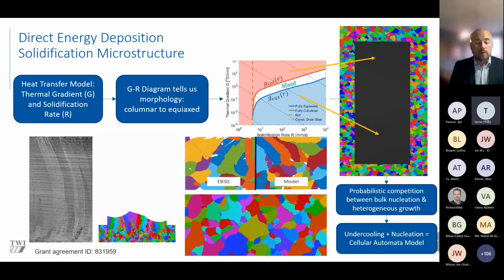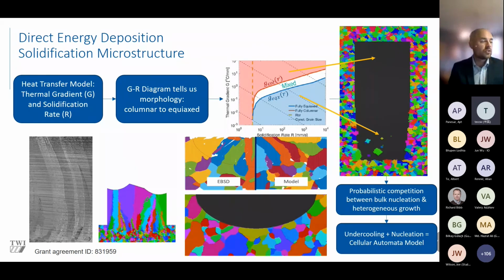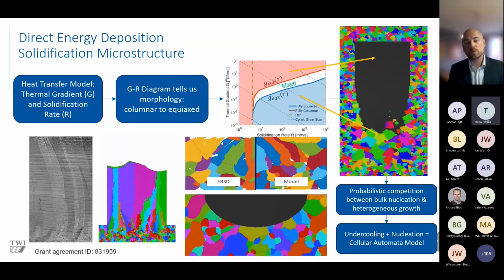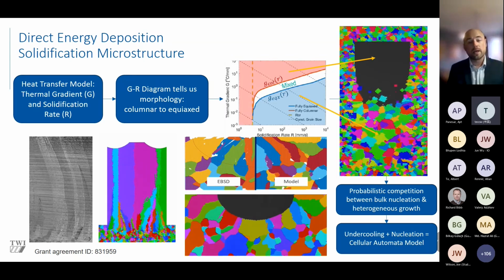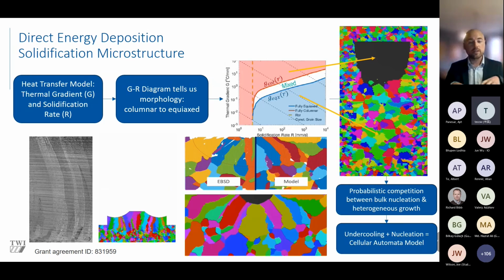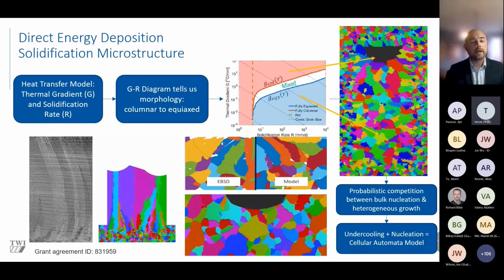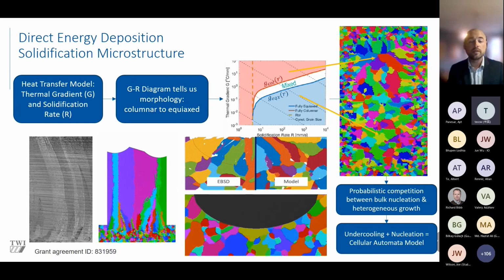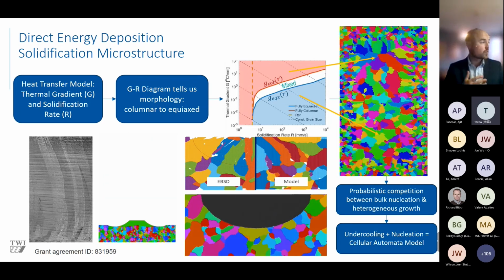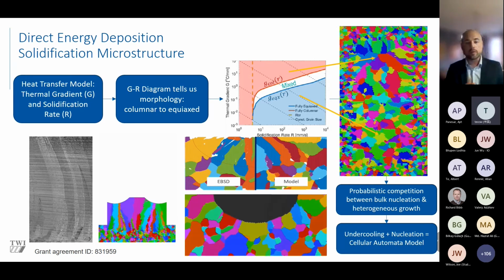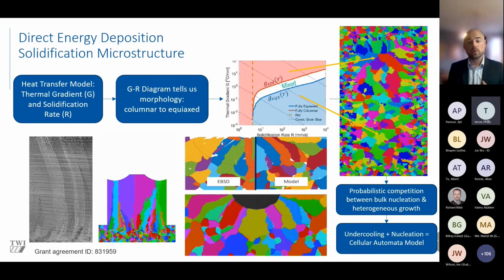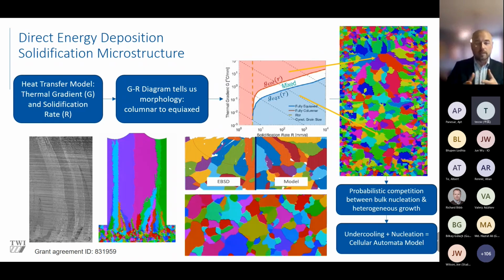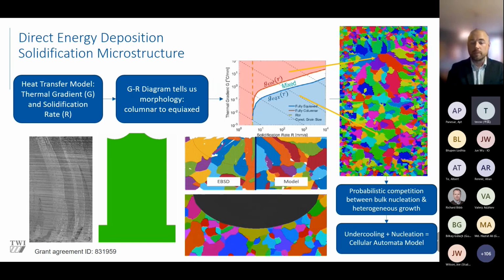And then with nickel-based superalloys and with direct energy deposition, there's a continuous challenge around lovely equiaxed microstructures and columnar microstructures. And we often get columnar. The grains just start selectively going taller and taller and taller, down selecting to fewer and fewer ones. And this can have a really detrimental impact on the toughness and the strength and isotropy, as well as the fatigue behavior. And there are what are called G-R diagrams, where we can look at how the thermal gradient and the solidification rate can trigger one formation or the other. And we can use that information and put it in a model and start to understand this dialing and changing of heat input with different geometric features to achieve a more consistent and uniform structure.